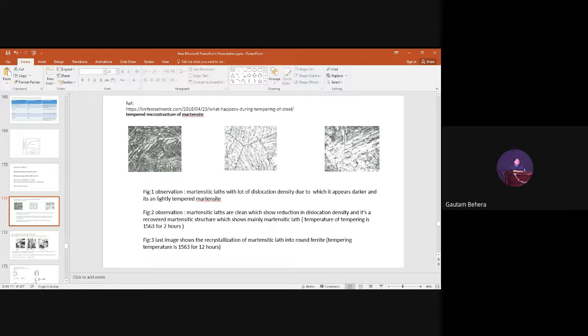And you have to remember that the martensitic laths or plates form on certain crystallographic planes. They do not form on random planes of the austenitic grains. They form on specific crystallographic planes, so they have a preferred orientation. These laths have preferred orientations; they do not form here and there in different orientations. That is also an important point to remember about martensite.